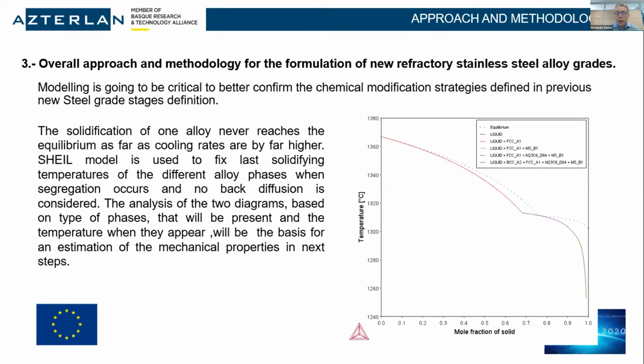What this modeling also allows us to do, the solidification that we have seen before was in equilibrium, but normally this never happens. The cooling rate is higher than a very slow cooling until equilibrium is achieved. There are other models that are used to fix last solidifying temperatures of the different alloy phases when segregation occurs and no back diffusion is considered. The analysis of the two diagrams, based on the type of phases that will be present and the temperature when they appear, will be the basis for an estimation of the mechanical properties and, in next steps, not only mechanical properties, also corrosion properties.